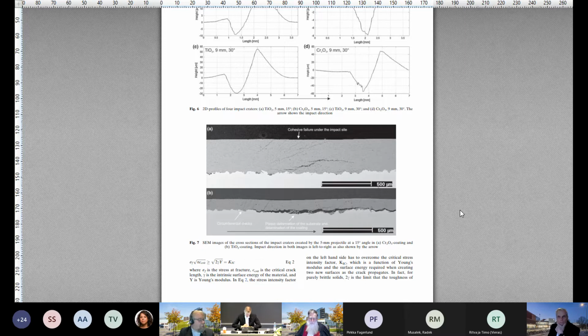So the real question is, rather than just thinking about the damage tolerance of the ceramic by itself, you've already proposed that you might be able to change the crack network within the ceramic. You've already proposed that you might be able to have some sort of composite coating. You call them spheres to blunt cracks. How about a strategy of having a bond coat that is ductile, or a subcoat, let's just call it the subcoat, that is ductile and that can act as a sponge to improve the damage tolerance of the overlay? What are your thoughts about that?